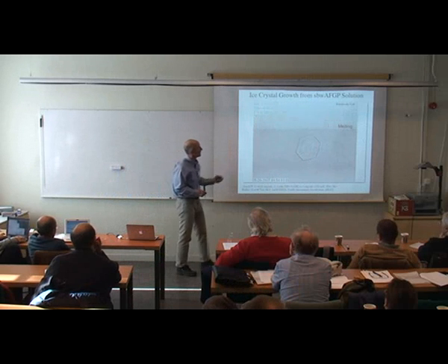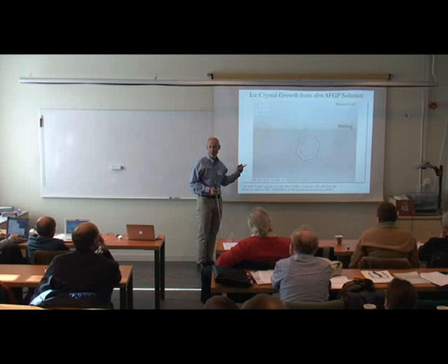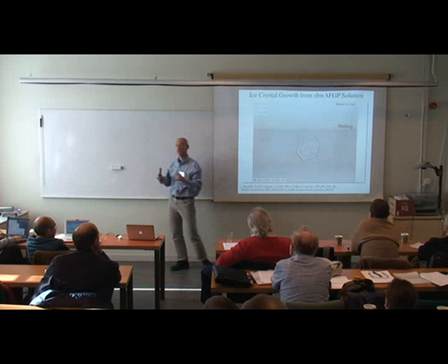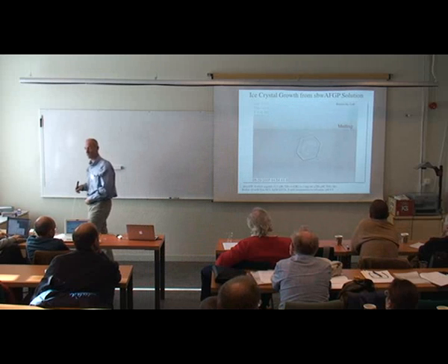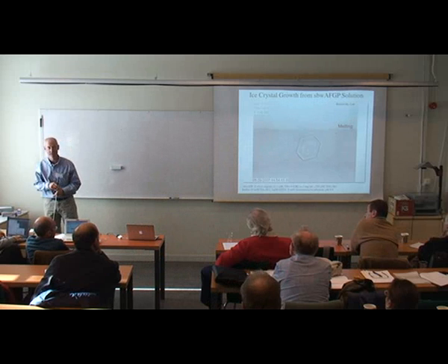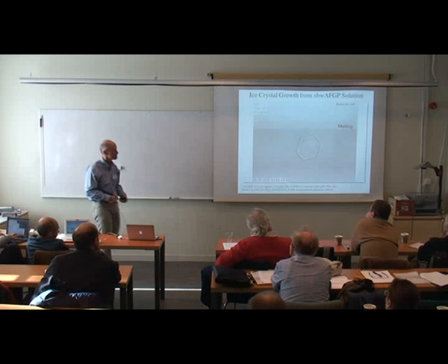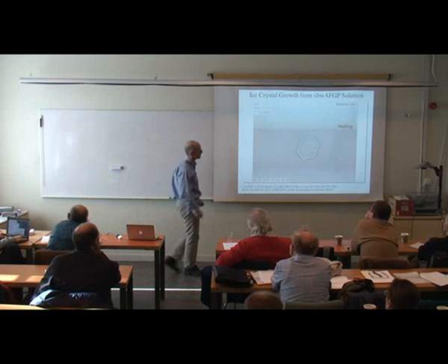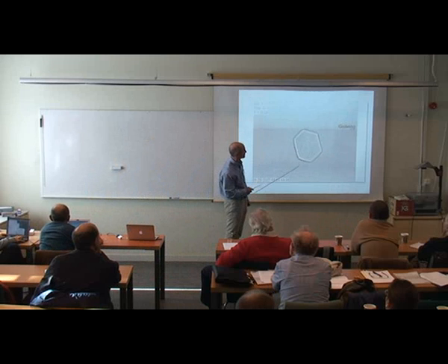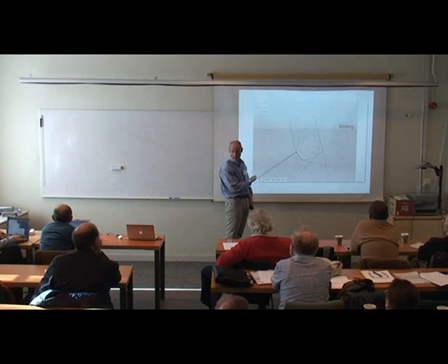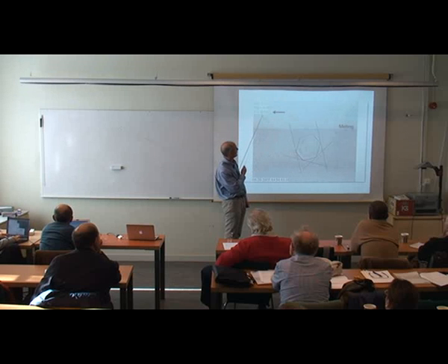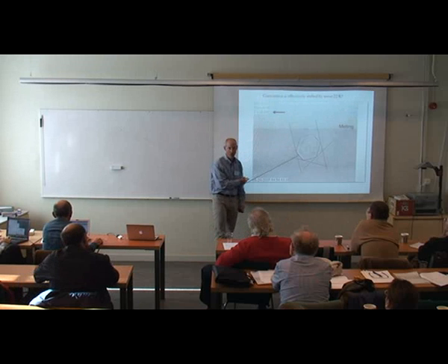If I do the same experiment by putting in a biopolymer called antifreeze glycoprotein. They exist in nature. They keep all sorts of organisms from dying. Okay? And I do the same experiment. Ido Braslavsky does. Melting, growing. I get this rotation. Okay? But importantly, this is 20 or so degrees above where we were for the pure case.